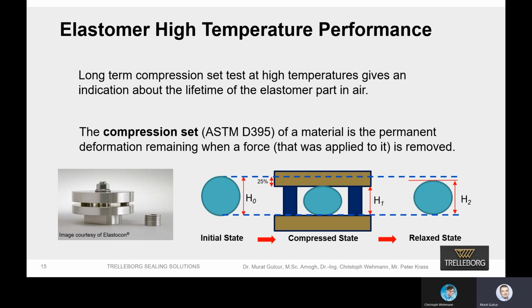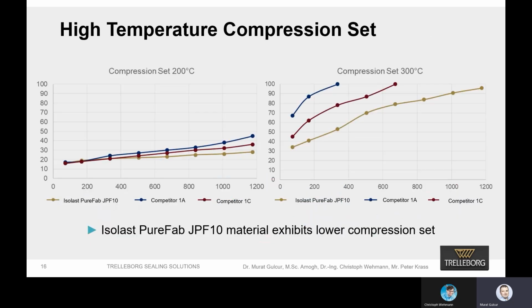While doing this test, we take the material, we compress it by 25 or 18%, and then put it in an oven at a certain temperature for a certain period of time. And then when we take it out, we measure the recovery rate, and then we calculate the ratio of deformation in percentage after the test. And then we end up with a graph like this.